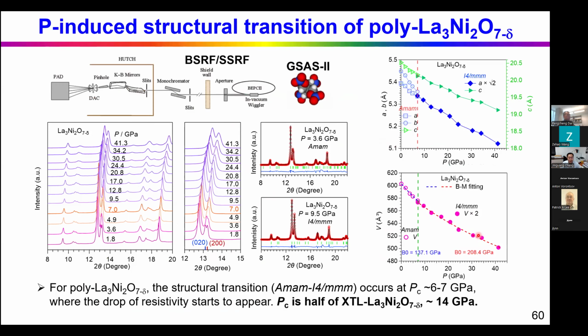Then we performed high pressure XRD for each sample, and we observed the structural transition. You can see the peak splitting in the orthorhombic structure is merged together in the high pressure tetragonal phase. For the undoped sample, the structural transition occurs at about 6 to 7 GPa, which is very close to the pressure where we observe the resistivity drop. And this critical pressure, PC, is about half of the single crystal, which takes place at 14 GPa.